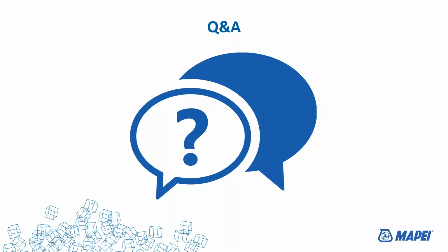Great. Okay. Will the heavy duty stripper work on enhancers also? No, not our enhancer. Once our enhancer cures, like our Enhancing Plus, at 72 hours, straight acetone will not take it off of the tile. It won't diminish the enhancement of this enhancer. So if you got a piece of slate and enhanced it and tried to remove it after 72 hours with straight acetone, you will not be successful.